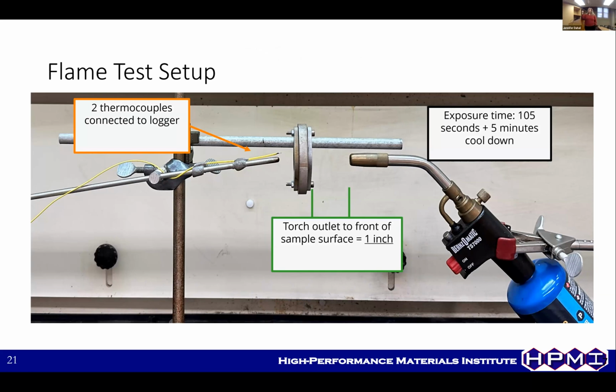We put in, this is a torch test. So we have our sample here that's clamped in these steel molds. We have 2 thermocouples connected to the logger, attached to the back of the sample, and then a 1-inch torch outlet in front of the sample surface, and then we turn on the torch and torch our samples.